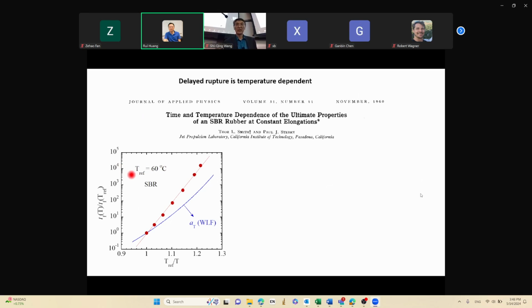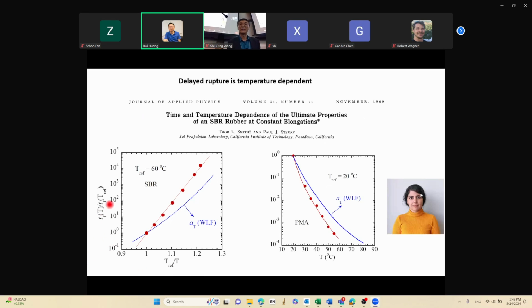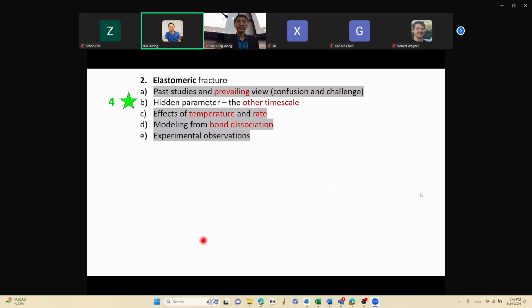Delayed fracture. This is the delayed fracture that shows how time secretly comes into the story. Stretch a piece of uncut sample, hold it at room temperature, it breaks in 10 minutes; hold it at minus 10 degrees, it takes you a week before it breaks. Okay, that's that data. If you look carefully, it doesn't obey WLF at all, by the way, quantitatively. Qualitatively, it might. I just replotted the data so it looks more dramatically different. This is our own data showing the same thing. Okay, so what's going on?